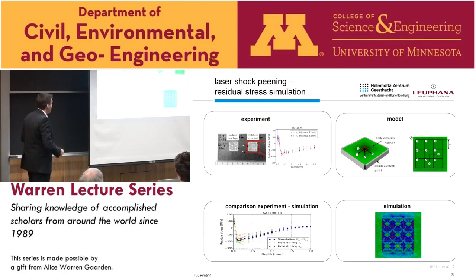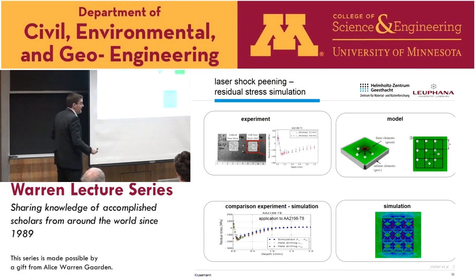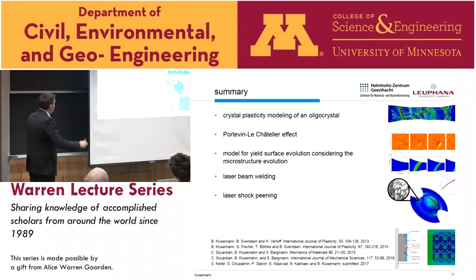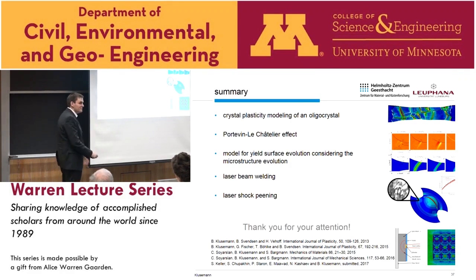We did then an identification for 2198 T3. So we have hole drilling experiments and our simulation, which fits very well. But we wanted to see, okay, is it also predictable. And we did that for a different material, in this case 2198 T8, which shows completely different material properties in terms of strength. And yes, we were able to predict the response quite accurately, so there is a faster saturation in terms of the residual stresses of these specimens.